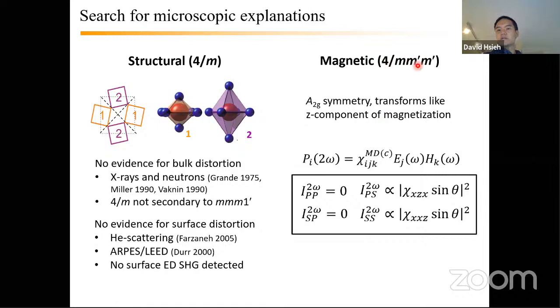And it turns out, we did all the tensor calculations for various processes respecting this point group. And what we found is that for magnetic dipole c-type radiation, governed by this equation where P equals chi MD c-type times E H, under this point group the response looks like this. In the P out channels, the response is forbidden, and in the S out channels, it's isotropic. So that's exactly what we see in the experiments.